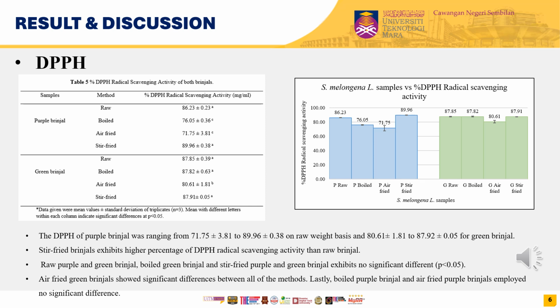According to the tabular data and the graph, we can observe the percentage ranging from 71.75 until 89.96 for purple brinjal, and 80.61 until 87.92 for green brinjal. And stir-fried brinjal exhibits a higher percentage of DPPH radical scavenging than raw brinjal. This method contributed to both colors of brinjal.